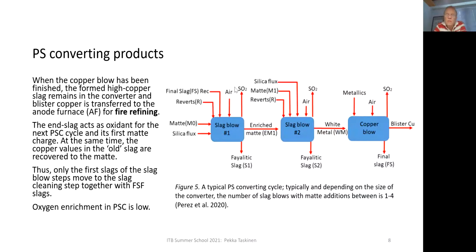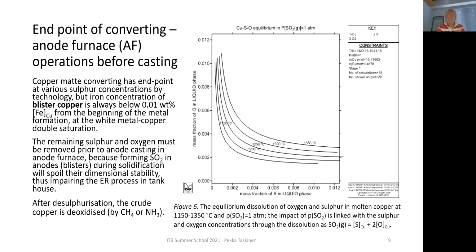So essentially the blowing gas is air with some extra oxygen, certainly increasing the productivity, but higher oxygen concentrations in the blow would damage the converter, and it is not practiced in industry at all. So what kind of material is blister copper? It is crude copper which doesn't contain iron anymore. Even the white metal, when it is saturated with copper, may contain 1% or 0.5% iron. So the blister copper generated from that is essentially iron-free.